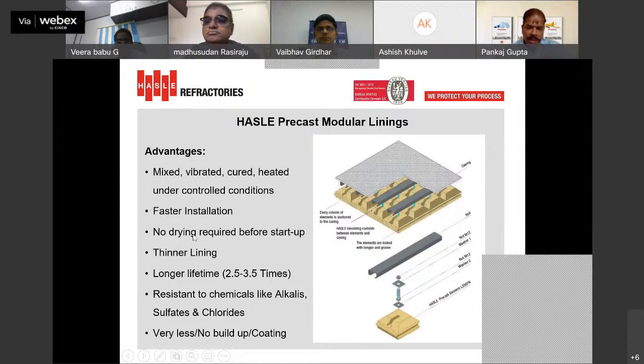No drying is required because it is already preheated. A thinner lining is possible. A longer lifetime can also be achieved, around 2.5 to 3.5 times, sometimes 4 times. We have observed it is resistant to chemical attacks from alkali, sulfate, and chloride, so very little or no buildup has been observed on the refractory surface.